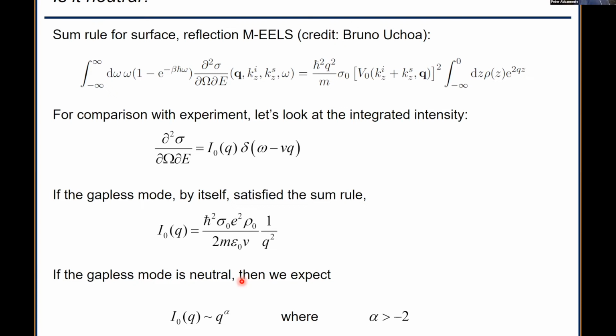This is something that Bruno Uchoa at the University of Oklahoma has been working on for about 4 years. And we now have a sum rule. We haven't published it, but it just uses the same techniques as in Nozières and Pines dating back many years. And this is what the sum rule looks like. There are various ways to express it. You can write a sum rule purely in terms of the response function. You can write the sum rule for the scattering cross section with the matrix elements in there and everything. In this case, we're going to compare to an experiment. So I'm going to focus on the sum rule for the cross section, which looks like this.